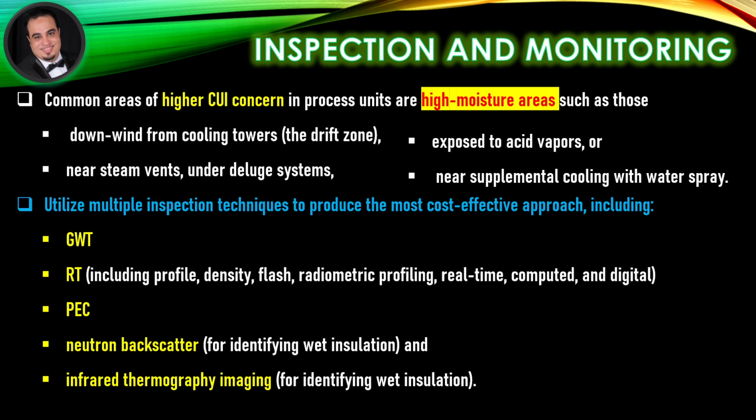Utilize multiple inspection techniques to produce the most cost-effective approach, including guided wave testing, RT, including profile, density, flash, radiometric profiling, real-time, computed, and digital. Pulsed eddy current, neutron backscatter, for identifying wet insulation, and infrared thermography imaging, for identifying wet insulation.